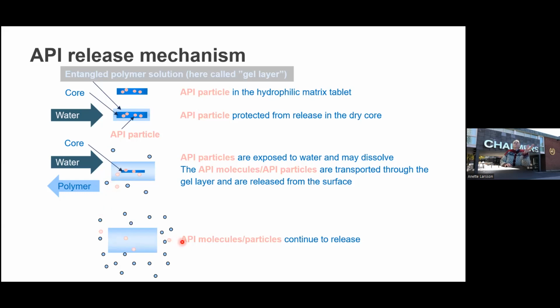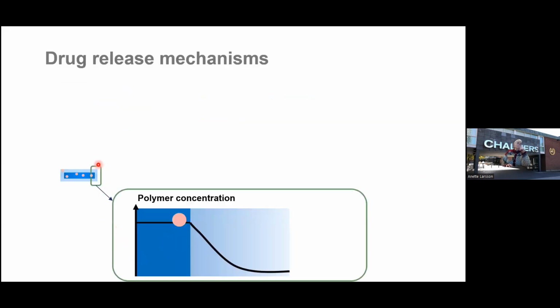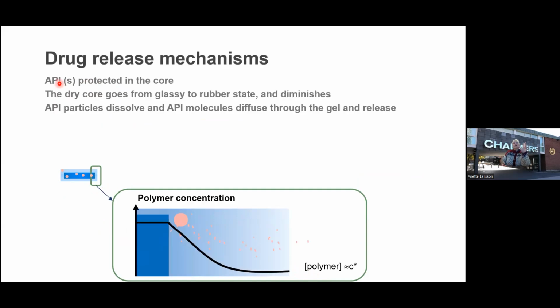When it comes out, then the API particles or the molecules are released. So that is how we have a transport out here. So now we should look into this a little bit more. So here we focus again. So we have the core and the gel, and here we start with the API particle inside the core, and we have the overlap concentration here at the surface. So the API is protected inside the core, but after a while the core has diminished and the API particles are now out in the gel. And now we assume that we have a very soluble drug. Then it starts to dissolve here, and you get it fully dissolved, and then the drug molecules can diffuse through the gel layer and be released to the bulk.